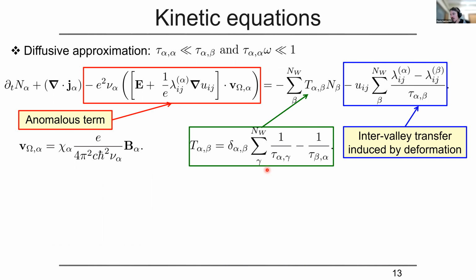There might be some numerical deviations, but in the end it should be the same. So it is not crucial to have a well-defined pair of nodes. The same goes for light penetration, because there the light will create this chiral charge imbalance, which doesn't depend on the Weyl nodes. Of course, the details of the calculations will be different, but the effects should again remain.